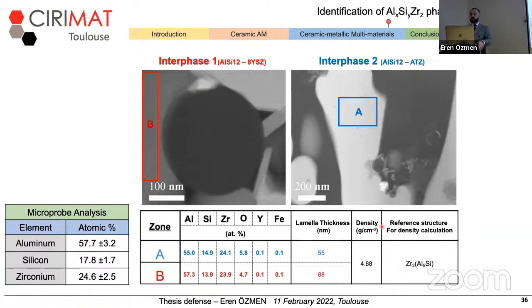So when I ran the calculation, I saw that it corresponds perfectly with the atomic values of elements that I detected in microprobe analysis. That helped me to say that the reference structure I took for this ternary phase can be a good candidate for the identification of this ternary phase.